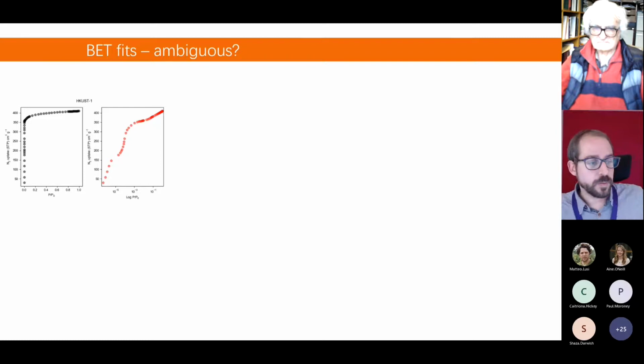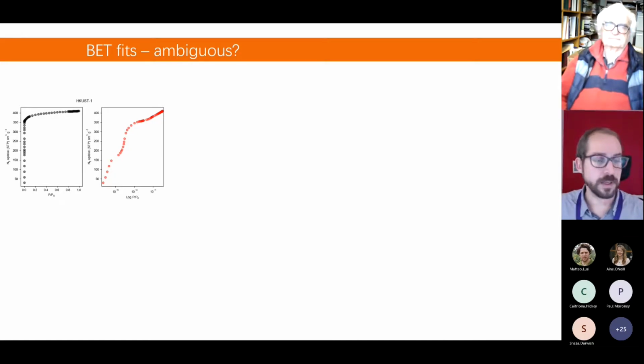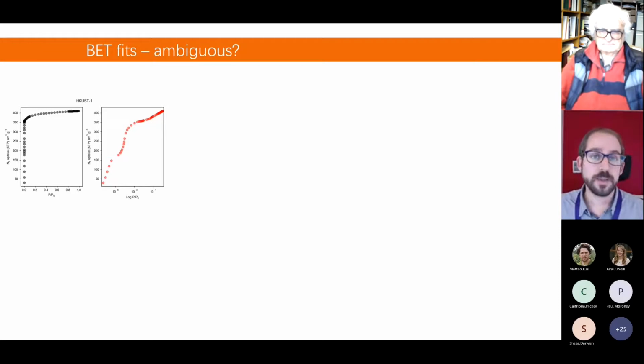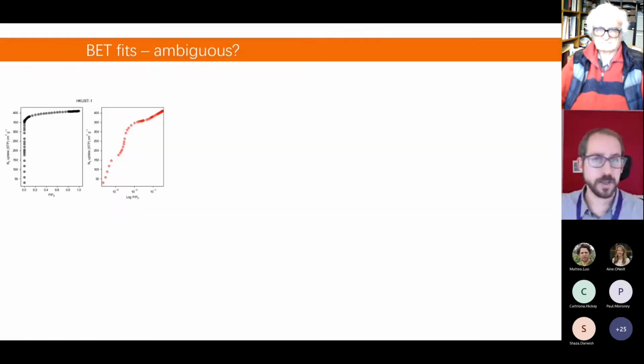Well, if you work with these porous materials, the typical technique is you have a nitrogen isotherm at 77 Kelvin. You can use different equations to characterize and to quantify different values. And the typical one is the use of the BET equation. BET was not developed for microporous materials, but almost any paper will include this figure. Otherwise, people will say, well, you need to include the surface area of the material. In microporous materials, surface areas are a little bit strange ideas, but it has some analogy and it looks like a surface area. It's a porosity at the end of the day that we can really explore.